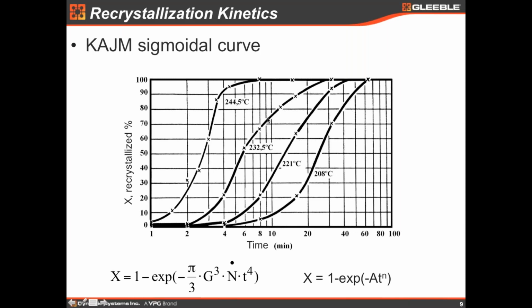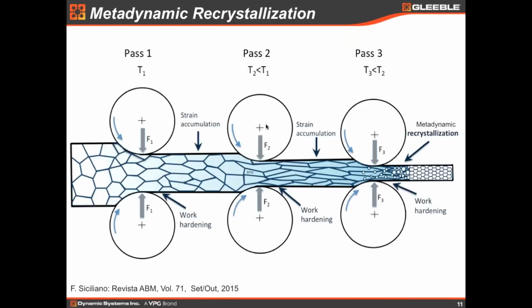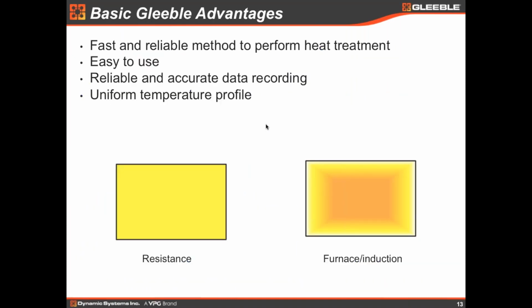We can easily have a gradient higher than 20, 30 degrees when you heat a specimen with a method different than resistance heating, which is uniform across the cross-sectional area of the specimen. So it's very easy to see that this has a remarkable effect on the rate and kinetics of recrystallization. So I think this is one of the main points for Gleeble. It's a very useful and suitable method to study recrystallization, besides being very reliable and accurate.